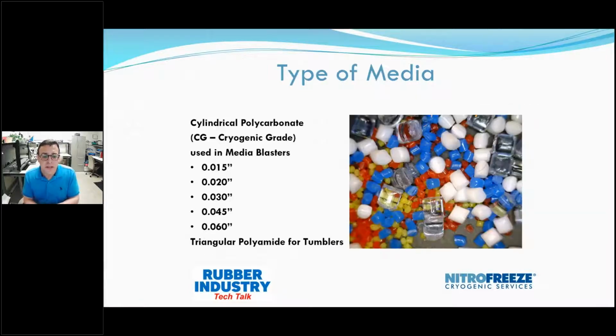Next, we have type of media. In the past there have been other medias, but for us in particular, and what I've seen the industry do here in the United States, anytime we're using media blasters, it's cryogenic grade polycarbonate media. And you can see this in the picture, different sizes, they range from 15 thousandths of an inch to 60 thousandths of an inch. The majority of what we do is somewhere between 15 and 30 thou. The 45 and the 60 thousandths of an inch media is used more on, what I've found, machine parts, hard plastics.